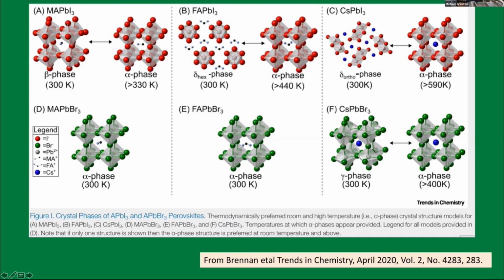But for methyl ammonium, you have the alpha and beta phase. That's tetragonal and cubic. They are very close, so they are stable. So that's why everybody uses methyl ammonium, okay? But in reality, people would like to use the inorganic one or the formamidinium, but you have to stabilize it somehow. For the bromides, it's not a problem, okay? You can see they all have a stable alpha phase at low temperature.